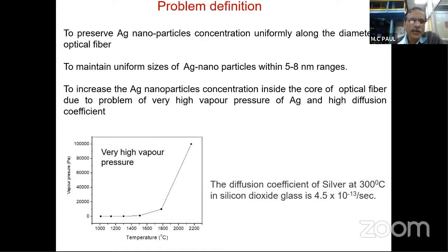The problem is that silver nanoparticles are very difficult to distribute uniformly within the core of the optical fiber, and the size should be maintained uniform. If it is greater than 10 nanometer, the loss of the fiber will be high. Another problem is that silver easily vaporizes at the high melting temperature used for making the fiber. So precautions can be taken.